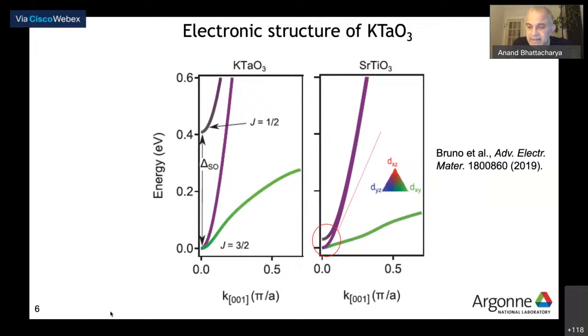Potassium tantalate and strontium titanate, being that they are both cubic perovskites and are t2g, all the electrons reside in the t2g levels, right? There, as you know, it's sort of an analog of the hole-like states of gallium arsenide, the valence states of gallium arsenide, but upside down. So you've got the J equals 1/2 spin split-off band and the J equals 3/2 manifold. They're separated from each other by the spin orbit splitting. That number is very small in strontium titanate, of the order of 20 millielectron volts. In KTO, it's very high. It's about 400 millielectron volts. Okay,